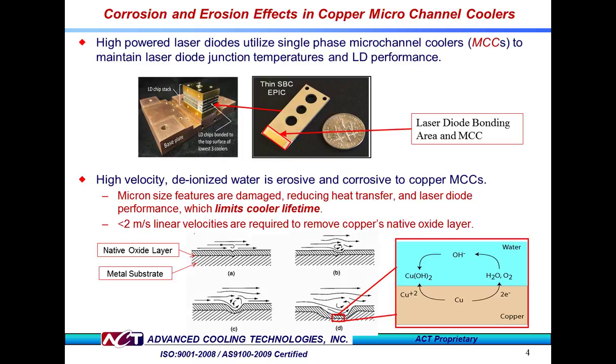Small defects, imperfections in the copper layer can become dislodged as a result of the fast flow rate. The particulates can build up over time, causing flow restrictions or clogging along some of the microchannel cooler's flow lines.